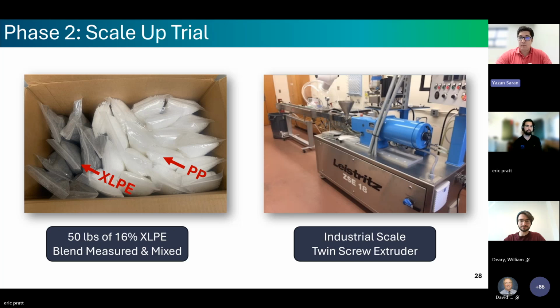We also, at this point, we were all out of time. We could not wait to receive more cross-linked polyethylene, so we made the decision to move forward with a 16 weight percent cross-linked polyethylene and polypropylene blend for our bulk sample. Thankfully, we found that this served our purposes just fine.